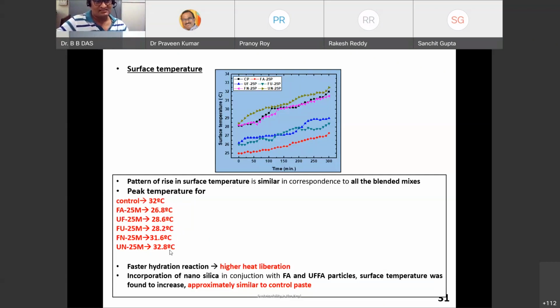Now, again, the problem is that when I add nanoparticles, at a very, very small scale, you can see the temperature rising again, almost getting close to the control, and that too on the surface. We were about to measure, and made a device to understand what is happening to the core temperature for a nano silica admixed cementitious composite.